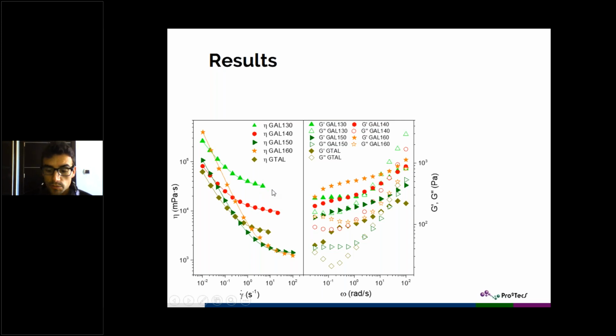values. As we pass from 130 to 140, that is a much more highly acetylated sample, we can see that we obtain more or less the same storage modulus, but a reduced loss modulus. So the relative elasticity has been increased. Also, we can see here a shift of the crossover to higher frequencies, and we obtain lower viscous values for this sample. So finally, our system is getting more compatibilized, so the relative elasticity of the network is being increased, and all the viscoelastic functions and the viscous values have been reduced.